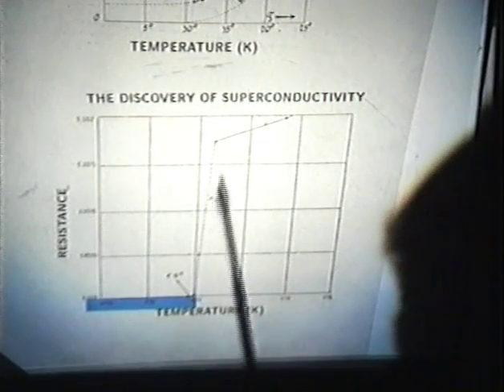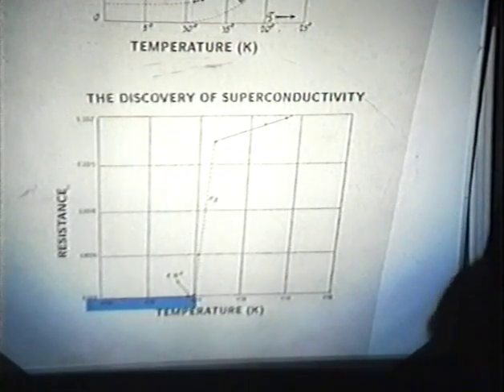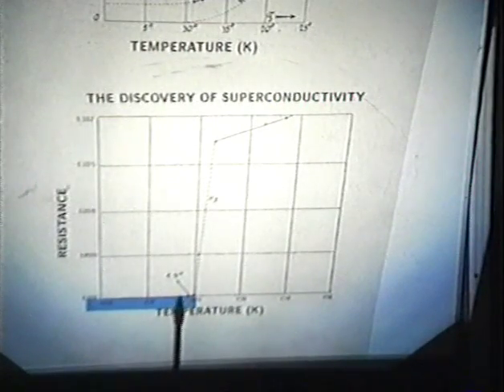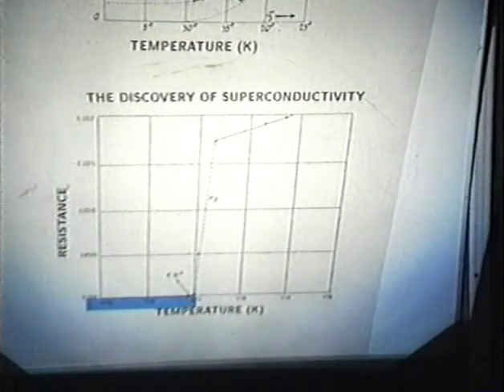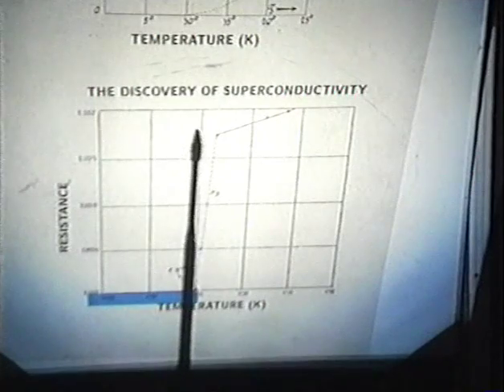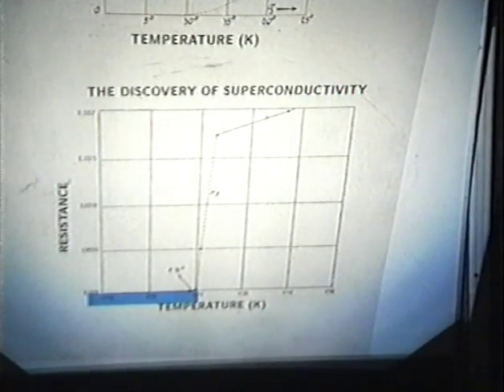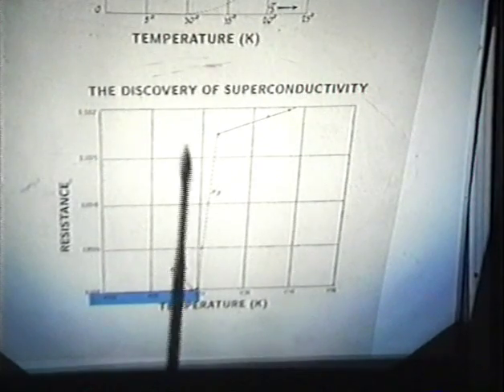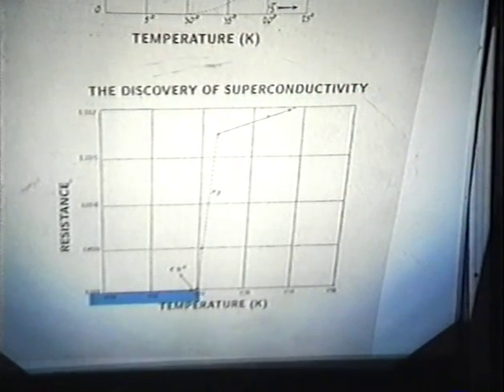Once they realised what was going on, that there was something new here, they began to investigate it. And the first thing to do was try and measure what really was the resistance down here. And so they did that by raising the current that they were using to measure the resistance of the mercury filament, and very strange things began to happen, because when they raised the current above a certain level, suddenly the resistance jumped back up to where they were expecting it to be. And this was very, very puzzling, and that's going to have significant implications for what we're going to discuss tonight, but nevertheless they soon recognised that the resistance had indeed disappeared, and they had discovered superconductivity.